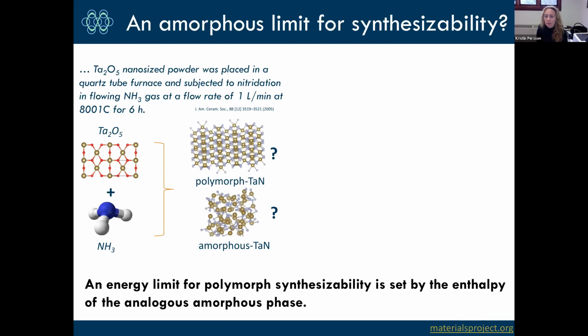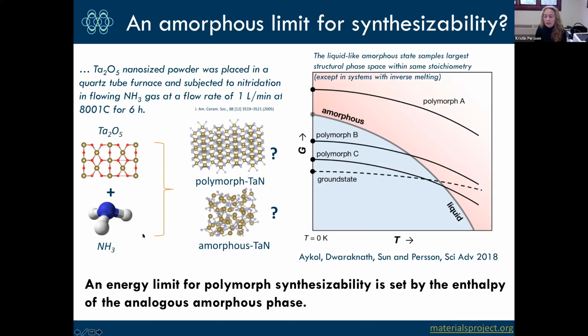And what I would postulate is that you can always kinetically make the amorphous gunk, because you're already breaking bonds in the tantalum oxide and the ammonia. So just scrambling that together, you have to do that anyway. That's always possible. But what about thermodynamically? What does the thermodynamic competition between the crystalline states and the amorphous state look like?